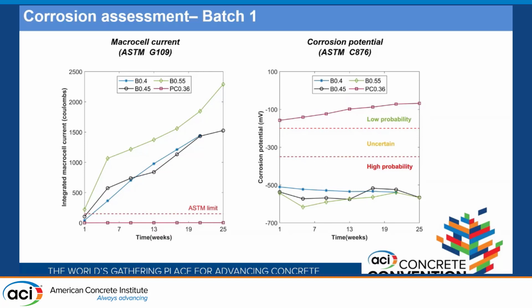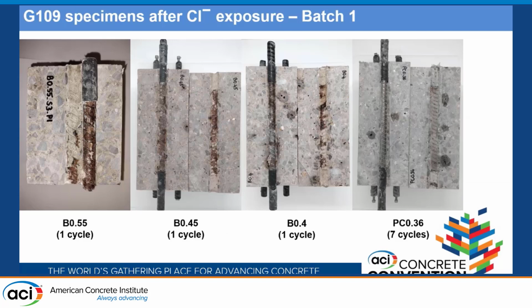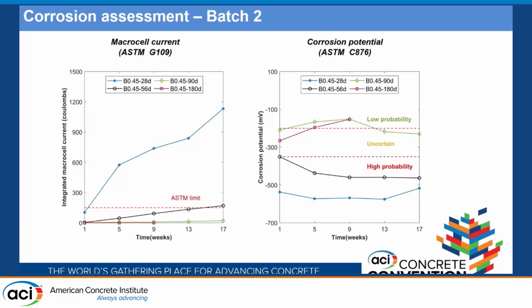So once the values were very high with just one cycle of exposure, I took out one of the specimens from the lot and autopsied it to see how the rebar looks. So the steel rebar looks like this. For all BCSA specimens with just one cycle of exposure, it seems to have a lot of corrosion going on on the rebar. Just a difference is that as the water cement ratio reduces, it seems to have a slight impact on the corrosion of the rebar itself. But if you see the Portland cement, which was exposed for 7 cycles of exposure, it still has no corrosion going on.